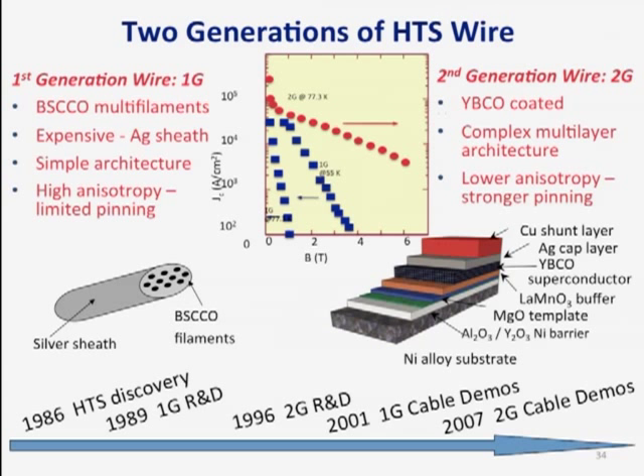These second generation wires are awesome. There are 2 ways of growing them. One is the RABiTS and one is the IBAD process. In any case, it's not silver. There's a teensy bit of silver there to help the growth. It's mostly Hastelloy, and there's the YBCO in here. This is not to scale. It's really 2%, but these are flexible. They're just hard to grow.